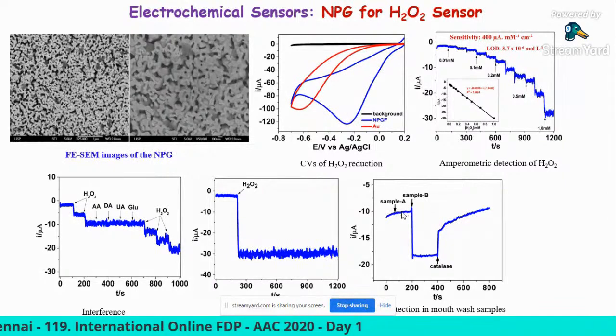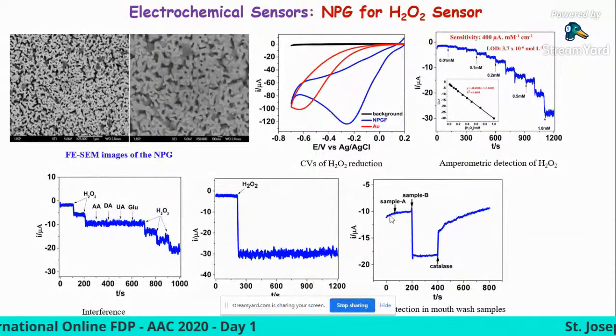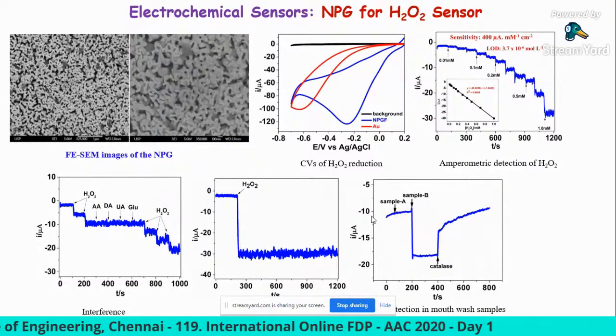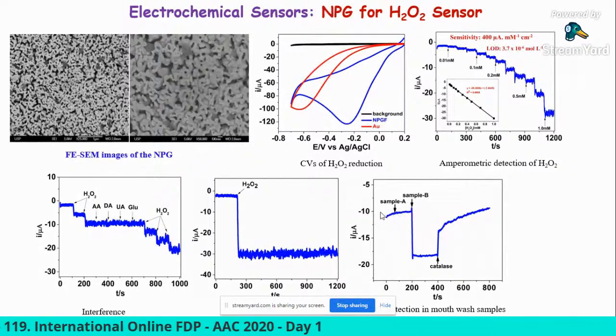I mean, it shows some current signal, but this is not due to hydrogen peroxide. This is probably due to oxygen reduction, because oxygen is also reduced at this same potential. All the laboratory experiments are performed after removing the oxygen. But here, this is the real sample, so we did not remove the oxygen, we directly used the mouthwash sample from the bottle. That's why there is some oxygen in the sample, so this current is probably due to the oxygen reduction.